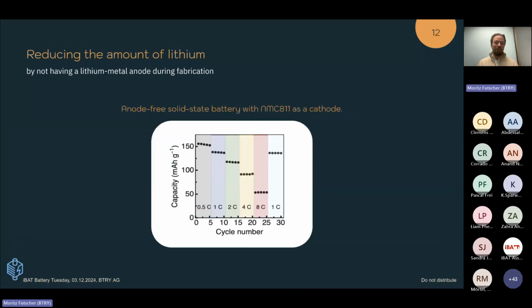And here you can see one example where we now combine both of these concepts. So this is now an anode-free thin film battery with an NMC 811 as a cathode. And you see that that works relatively well. We have very stable cycling performance here and with reasonable C rates. And this was actually one of the first measurements which I've done together with Abi when I joined Empa a few years back. And then we really looked into all of these concepts in more detail.